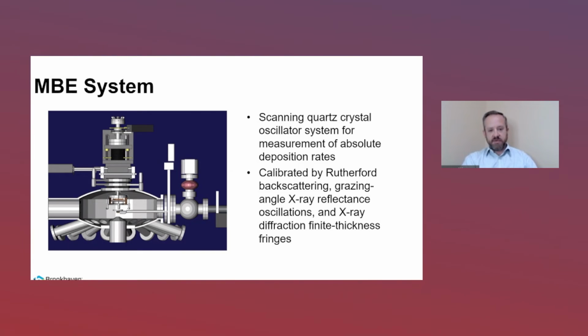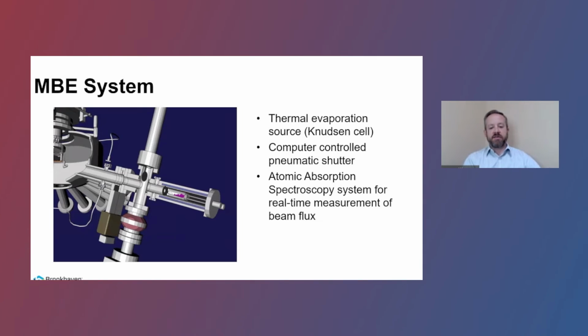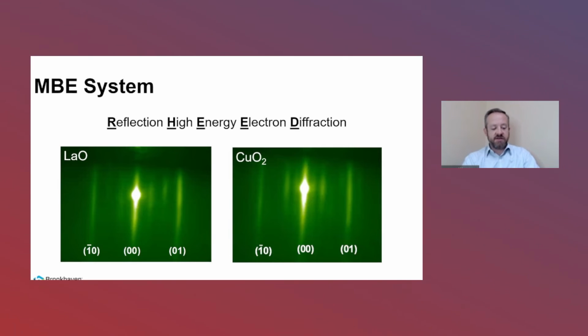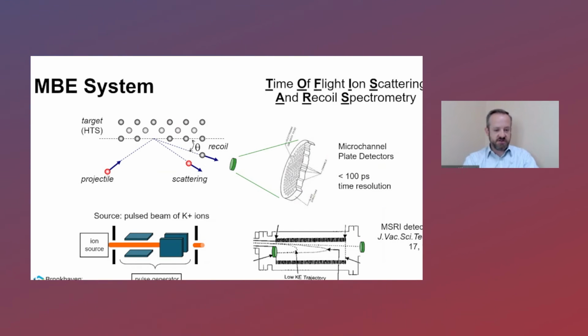And this rate information then is used by the computer that controls the growth and controls the pneumatically actuated shutters that are on each source to meter out a precise amount of material to the substrate surface, and helps us to control the growth very finely, to less than 1%. The chamber is fitted with a few analytical tools as well. RHEED, which gives some crystallographic information, standard for molecular beam epitaxy systems. We also have a time of flight ion scattering and recoil spectrometry system, which gives some chemical information if needed. You pair all that with the most important ingredient, which is the years of experience gained interpreting the data coming from these tools and steering the growth. And we have a system that allows for atomic layer by layer growth.